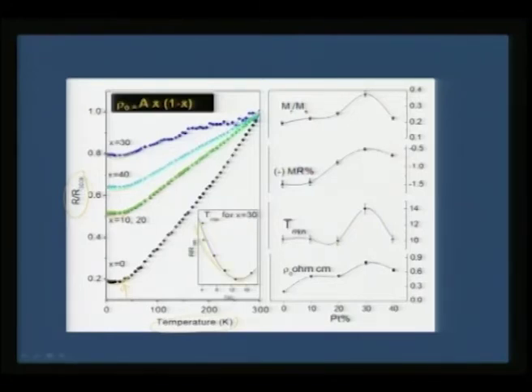Now if you look at the T minima that we are talking about, and if you try to plot this T minima as a function of platinum concentration, you would see only for a 30% cobalt platinum alloy, the T minima is more pronounced, and also the residual resistivity seems to be more pronounced only for 30%. As a result, if you plot the MR by MS from the hysteresis loop, you also see the same trend for the cobalt platinum alloy, and as a result the magnetoresistance ratio seems to be maximum only for 30% platinum doped alloy.